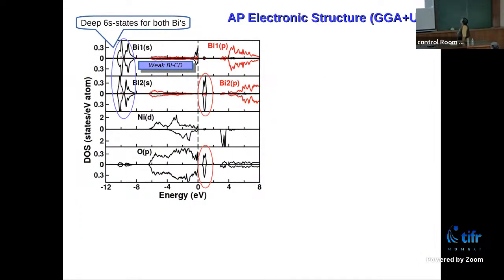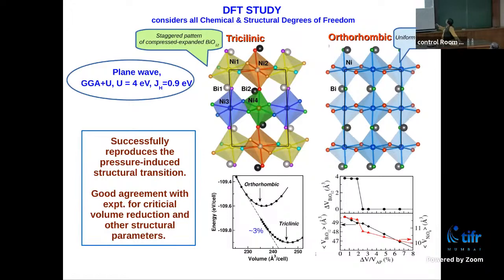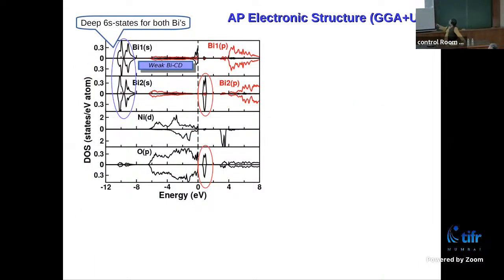Now, we look at the density of states of the ambient pressure phase. Just for those who are not used to seeing density of states, this has two panels, and each panel has up and down spin channels. And projected to bismuth 1 in the ambient pressure phase, I forgot to mention, in the ambient pressure phase you have two different bismuths, with two different sizes of bismuth polyhedra, one large and one small. In the high pressure phase, there is only one kind of bismuth, and you have uniform bismuth oxygen polyhedra. So first of all, we find that both bismuth 1 and bismuth 2 have this deep 6s state. So that means it is indeed not possible to make the bismuth 6s empty.